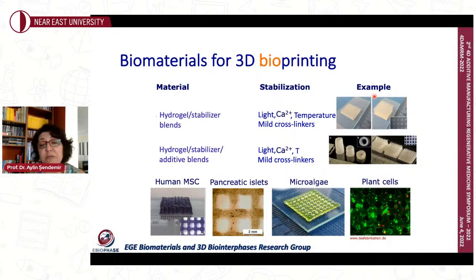But when we talk about temperature, we're talking about around 37 degrees. Because as you know, if we reach even up to 40 degrees Celsius, we would lose cell viability. So we're talking about minor changes in temperature, minor changes from room temperature, and some mild cross-linkers, like some biological origin cross-linkers, are also under investigation.